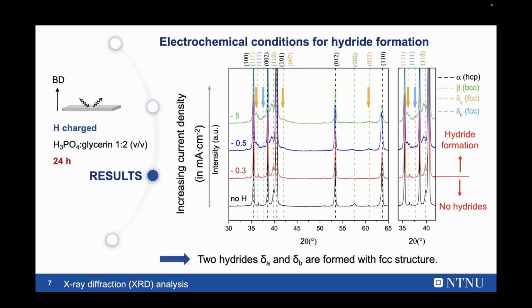And here it's interesting to see that two hydrides were formed, both with the FCC microstructure. Nevertheless, it was reported that for additively manufactured titanium alloy, these two hydrides were recently reported for the first time, and they have different lattice parameters compared to the delta hydrides that were observed in conventional alloys.